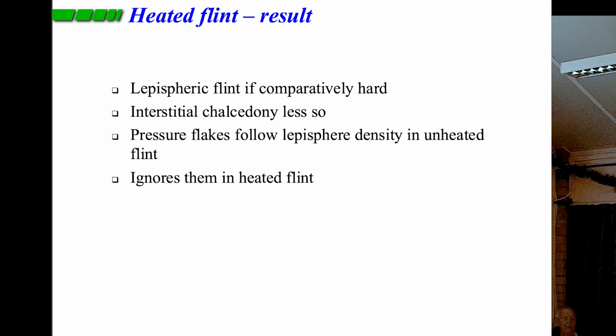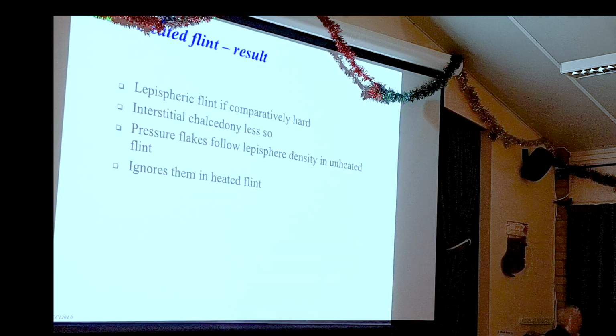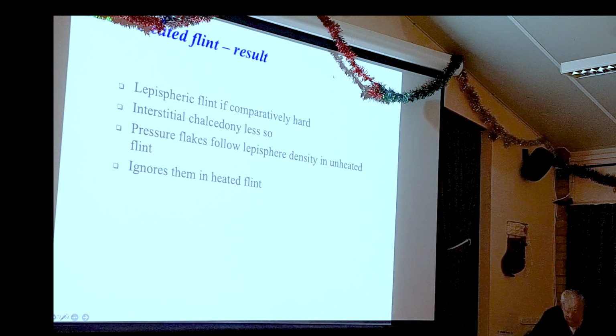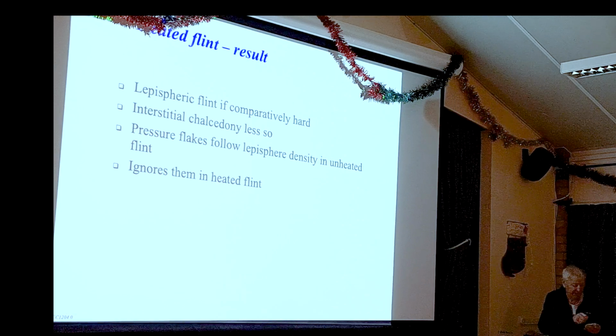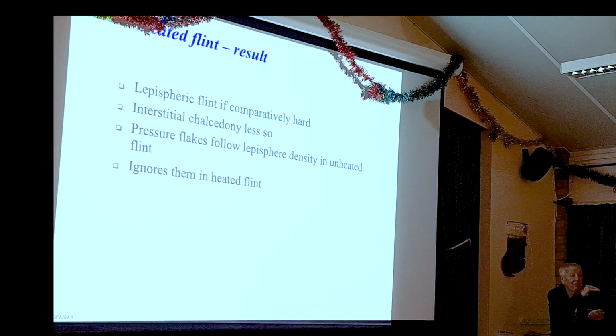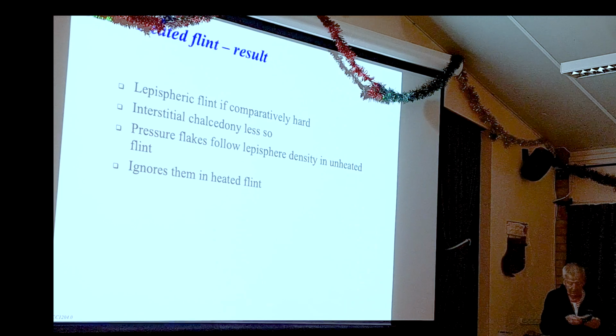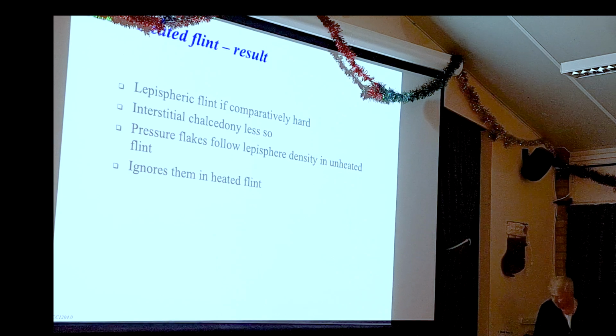What happens is that if we have untreated flints, the chalcedony is very soft compared with the lepispheres. So every time we hit a clump of lepispheres, everything diverts sideways. When we're pressure flaking, what we do is the archaeologist will sit down with one of these and a stick and then using pressure just flip off detailed flakes around the edge. And it's not very good with some samples, but heated flints, it becomes a lot better.